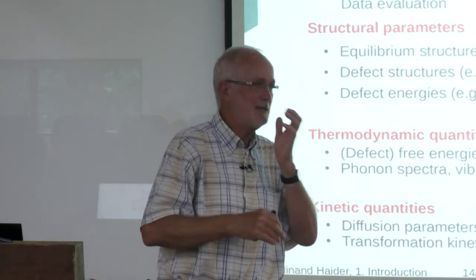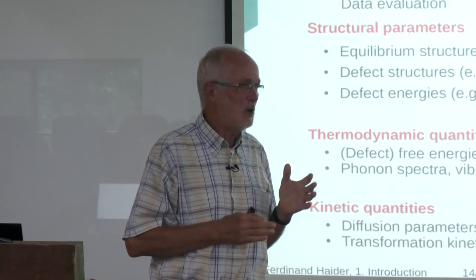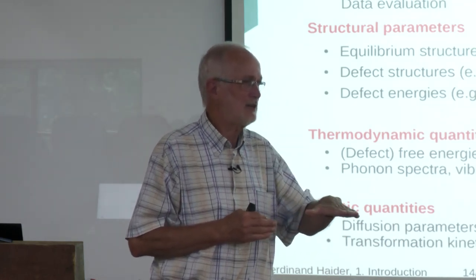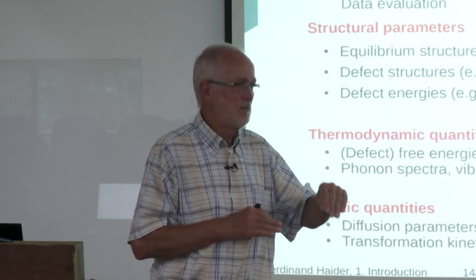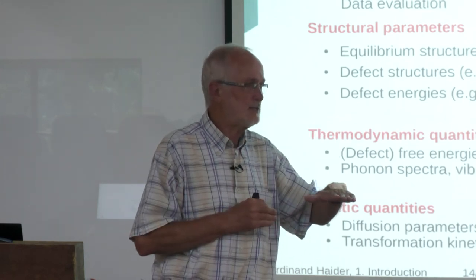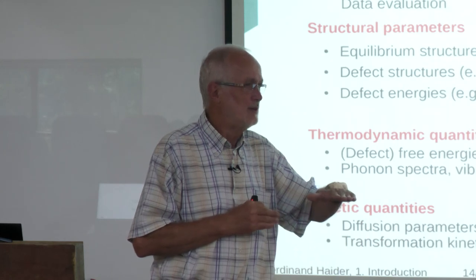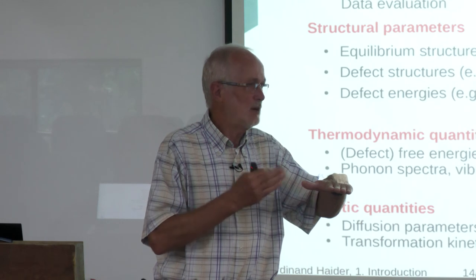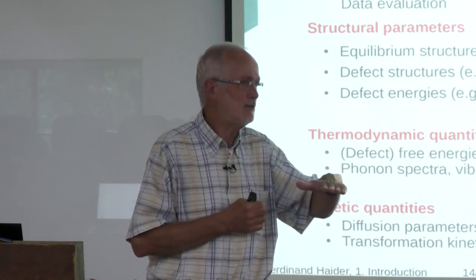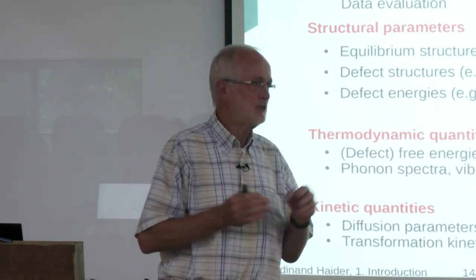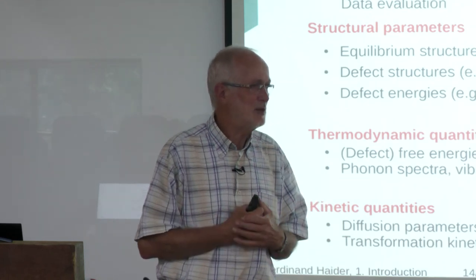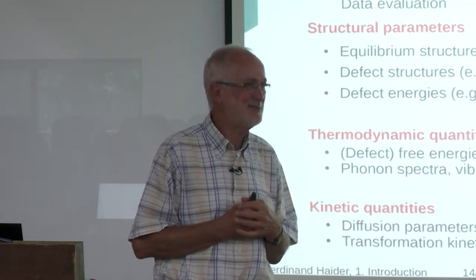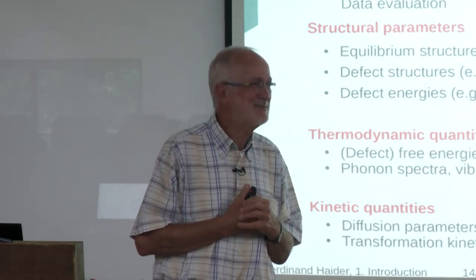And the same happens in molecular dynamics. You always have to struggle with undercooling if you want to study such a solidification phenomenon. You have a critical nucleus size, which is not very small. And since your system is small, you have problems to form a large enough nucleus. There are tricks around it, but that's one of the limitations, I would say. I'm not sure whether this was your question, but at least I answered something.